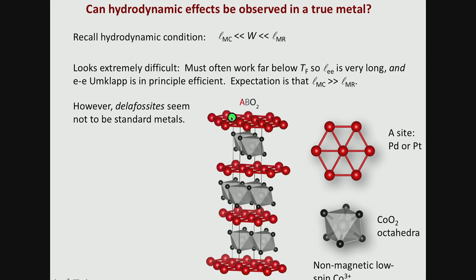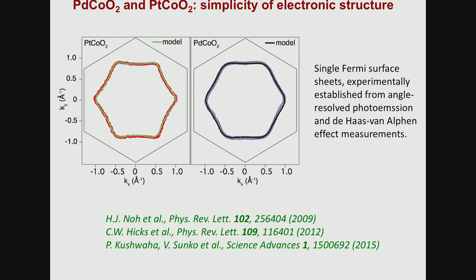They have triangular lattice layers, either in the metallic ones of palladium or platinum, and in the simplest ones of all, you have cobalt oxide octahedra, which are completely non-magnetic, just acting as separators to make the metallic layers sit a long way apart and give you a two-dimensional material. Because they're two-dimensional and very pure, they give fantastic photoemission, and we've been able to categorize the Fermi surfaces in a lot of detail with photoemission experiments. They're always hexagonal cylinders, very two-dimensional materials. And the degree of faceting of the cylinders changes slightly from material to material.